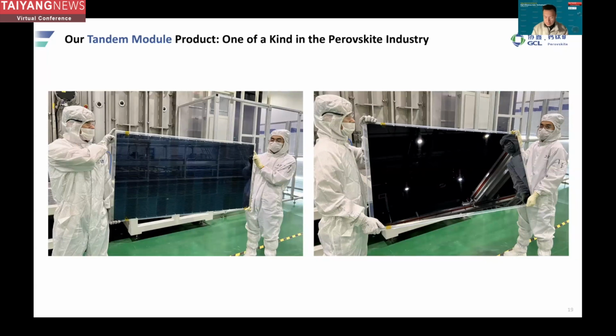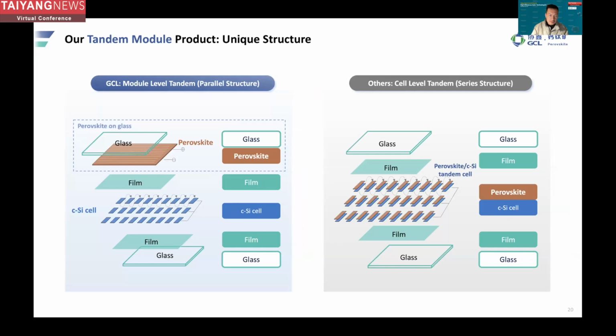And our strategy to construct the module is that we deposit the perovskite layer on this top glass. That's the complete structure for the perovskite module. And after we construct this perovskite module, we construct the silicon module here, and then we put them together to make a tandem. So this is a module-scale tandem. That's the module to module tandem. And these two modules are matched by the voltage. So it's a parallel connection.